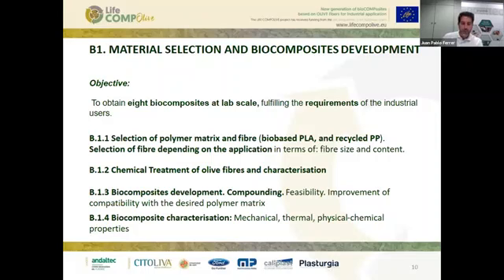This action was divided in 4 sub-actions: B1.1, selection of the polymer matrix and fiber. And the polymer matrix can be of two types. We have used bio-based polylactic acid and also recycled polypropylene. And we selected the polymer matrix and the fiber depending on the application. So the fiber was selected in terms of size and content.